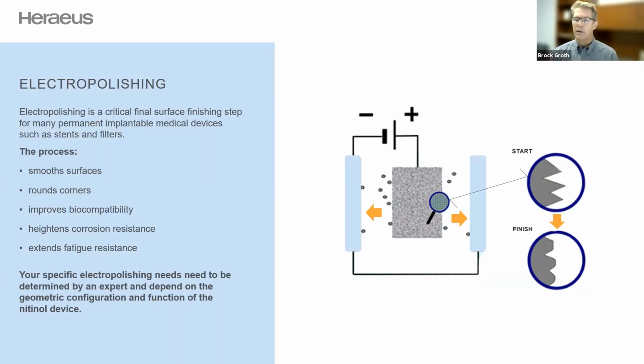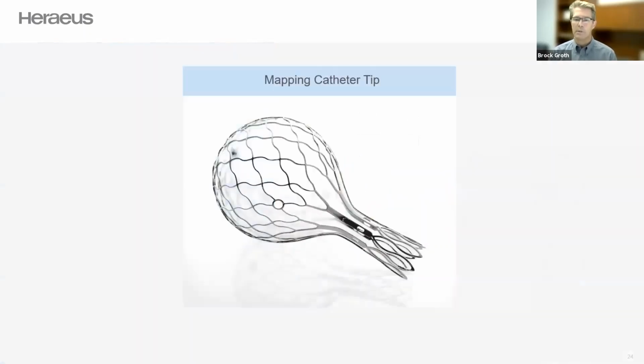And also, this smoothing will improve your fatigue resistance. Cracking in fatigue is basically crack propagation, and if you have a smoother surface to start with, you will have less opportunity for a crack to start, and then that alone means that your crack propagation is going to be delayed, and electropolishing will improve your fatigue performance. Again, there's a lot going on here, but it's a very, very useful process for many, many implantable devices. Heart valve frames, left atrial appendage devices, stents, you name it.